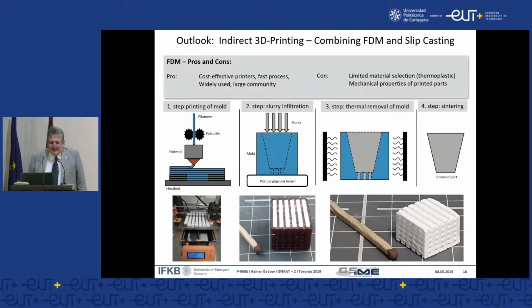And here we have filament deposition modeling. What does it mean, a filament? We take an appropriate plastic material, we fill it with these ceramic species, and then by an extrusion machine it becomes a very fine cylinder, a few kilometers in length on a big wheel, and by a high precision drive, this material is extruded, and the thermoplastic material is heated in the head. So the printer is a micro extruder, so that the structure is built strip by strip.